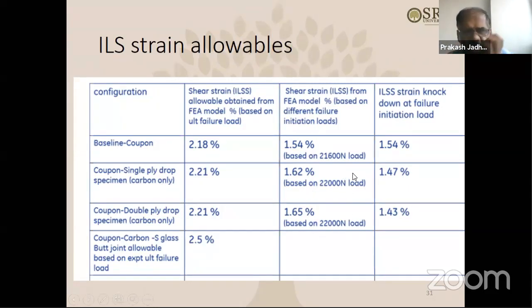There's a big difference between the initiation failure load strain and the ultimate failure load strain. You can see the big difference there. And also you can see the ply drop effect. So it's almost like it's changing by, let's say, 10%. The comparison I'll show you later, like how much it affects.